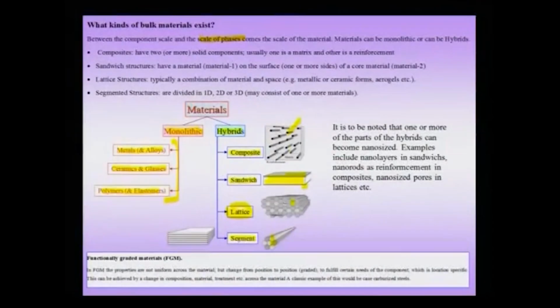On the other hand, in the case of a composite, just one of these components could be nanoscale, and of course, there is no stopping us from putting, for instance, 2 or 3 types of reinforcements, and therefore, one of these reinforcements could be in the nanoscale, or 2 of these reinforcements could be in the nanoscale. For instance, suppose I am talking about reinforcements which are particles and rods, then the particle size could be in nanometers, the rod diameter could be nanometers, but not the rod length, which could be much larger. The important thing here is that one or more of the components could be in the nanoscale, and not the entire composite or the entire sandwich structure.